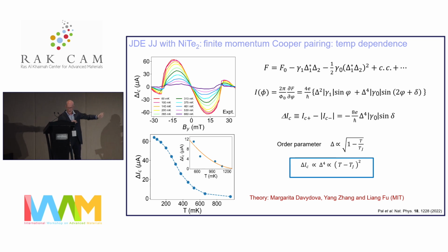The field we apply is needed to break time reversal symmetry, which is a prerequisite for seeing this diode effect, as is broken inversion symmetry in the material, which is obtained in both cases through the topological surface states, we believe. Those topological surface states in the presence of a small field develop a spin asymmetry, and that spin asymmetry is locked through spin momentum locking, through Rashba effects at the interface, which I don't want to discuss, akin to the discussion from Claudia.